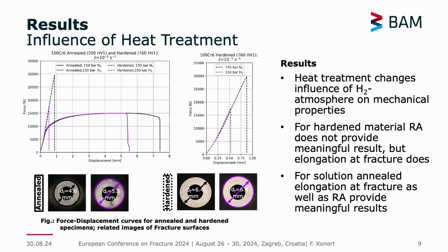And you also see this in the bottom left picture, that you have a really clear reduction of area. But if you go to the hard material, you don't have this reduction of area anymore. So this way of interpreting the hydrogen effect would not be suitable if the material behavior is fully elastic. But of course, you have a clear decrease in strength here due to the hydrogen effect. So the point I want to make here is that it depends a bit on the material behavior in general how to interpret the results of the tensile tests.